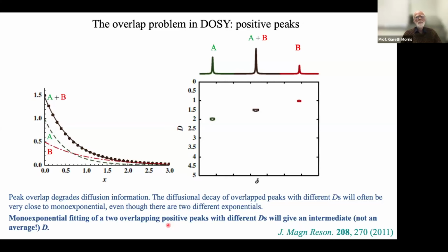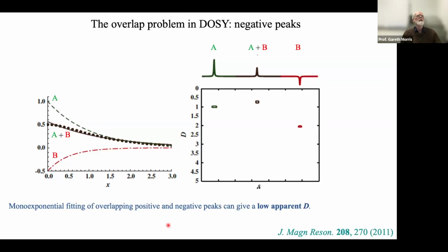And this slide says positive peaks, which implies that we could have negative peaks. And yet, in most circumstances, we shouldn't get negative peaks in the DOSY experiment. We're taking a spectrum and we're gradually attenuating the signals in it. But there is one reason why we can easily get negative signals in practical experiments. So let's think about what happens if we have a negative signal and we get overlap.